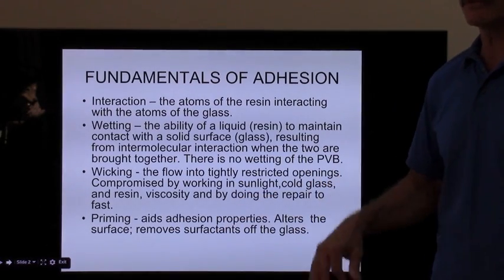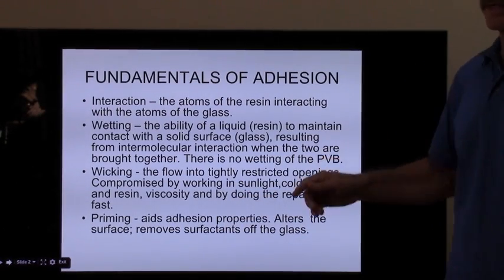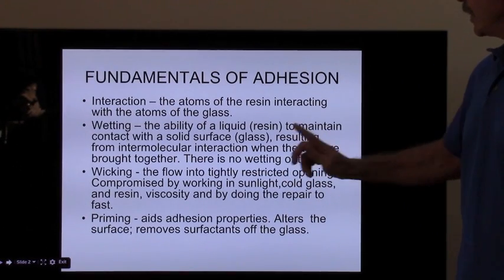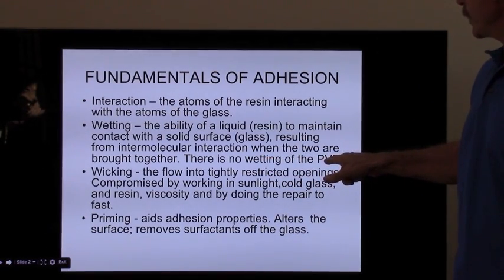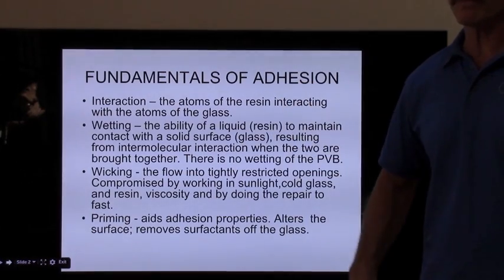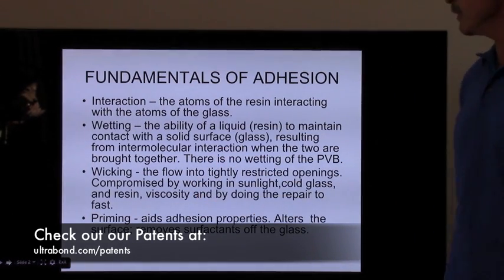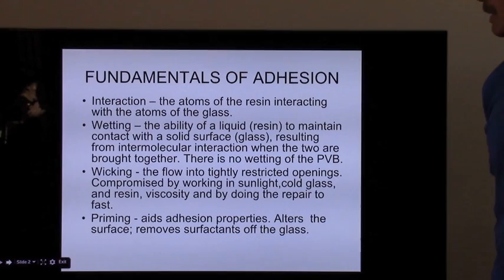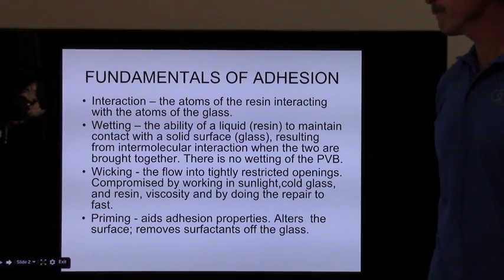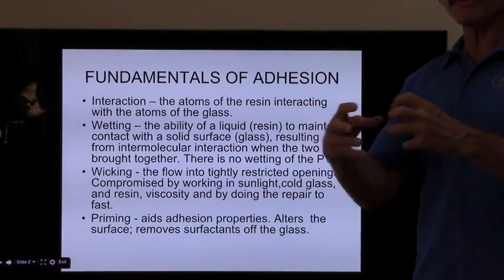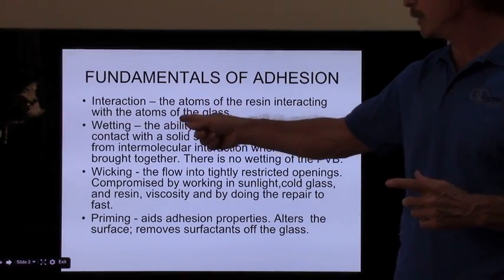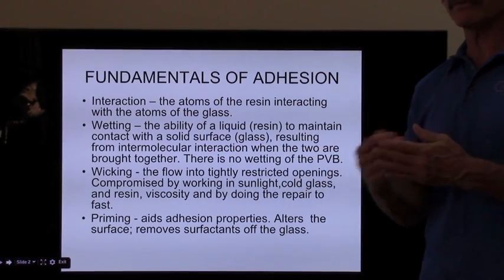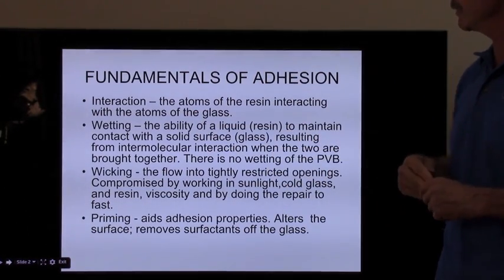Ultrabond has addressed this both in the cracks and in the repair of stone breaks. In fact, it was addressing this issue that is why we have 20 windshield repair patents. Many of those were solving the problem of resin not staying on the PVB. So what happens when you inject resin into a crack? The resin is made up of molecules, and these molecules are going to interact with the atoms of the glass, because again, the resin is low surface energy, and the glass is high energy.